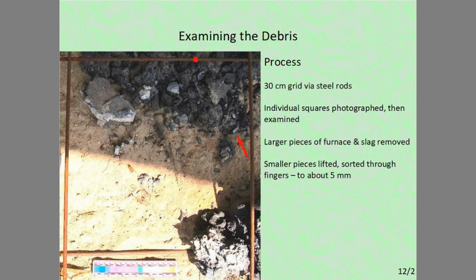Back to the intent of this experiment, which was discovering any bone fragments remaining after the smelt. The process used was first to lay out the working field using a set of steel rods to map 30 centimeter squares. Each one of the squares was individually photographed and then examined for any remains. This was accomplished by first removing any larger pieces of furnace or slag. Then individually the fine debris was screened through the fingers. This allowed us to have a resolution down to about 5 millimeters.